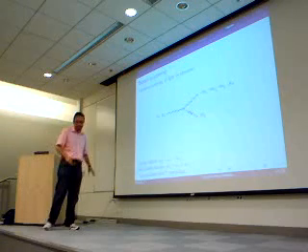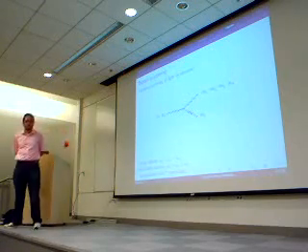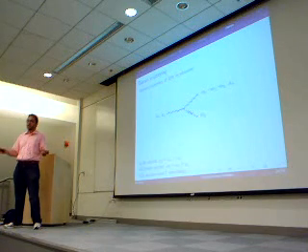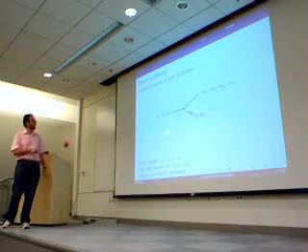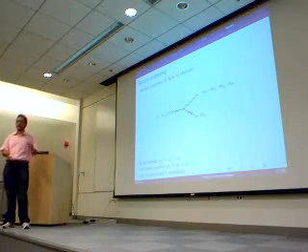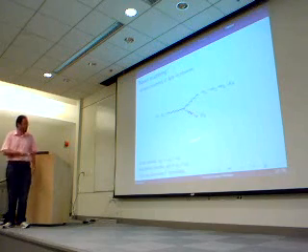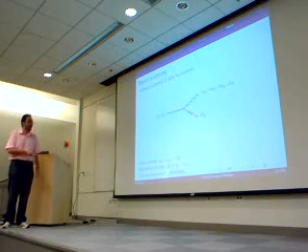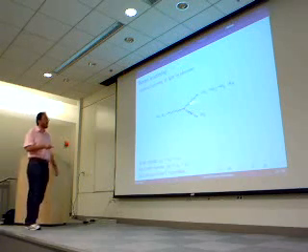Also in this case, because of the big difference between the wavelength of visible light and the size of the primitive cell, only phonons near the gamma point contribute to this process.